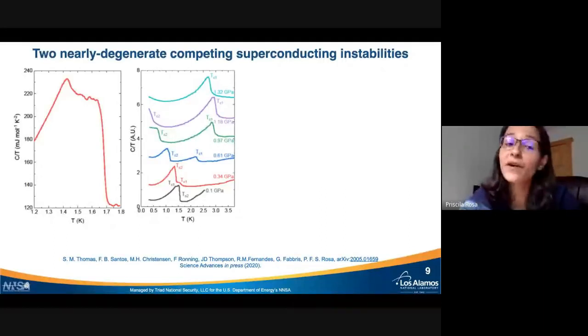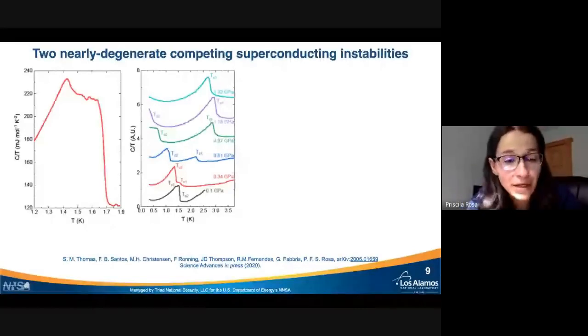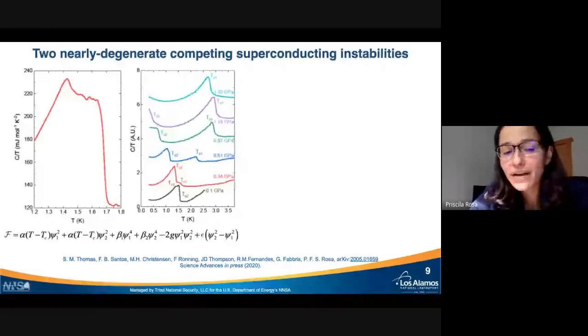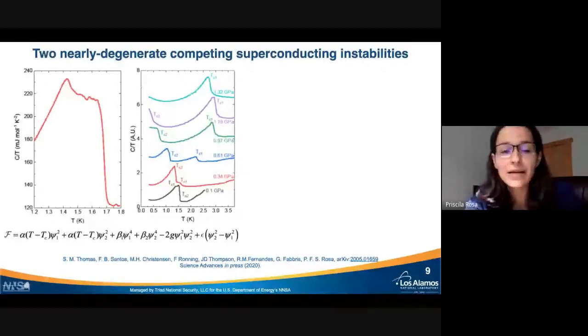And this has very important implications because this is an orthorhombic material. So there are no degenerate representations of this space group. So if we have two phase transitions, then we have to have two nearly degenerate competing superconducting instabilities. So that's a very good constraint for any theory, and we started actually with a phenomenological theory, so we can write down the free energy for those two competing instabilities.